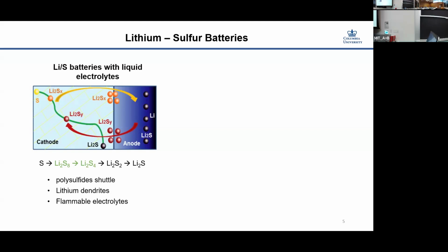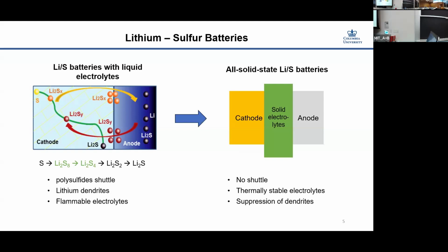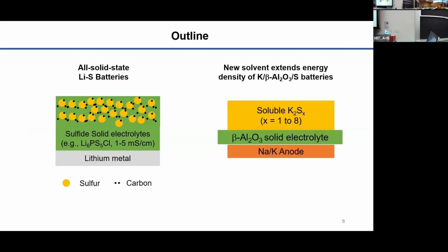There are also other issues, for example, formation of lithium dendrites, which is a safety problem, and also the ether electrolyte is very flammable. So a very clever and straightforward strategy to solve this problem is to have a solid membrane between the two electrodes. In this way, even if you have polysulfides, they cannot diffuse to the negative electrode to cause side reactions. Also in general, solid electrolytes are more thermally stable than liquid electrolytes. They also have high modulus, which can help suppress the dendrites.